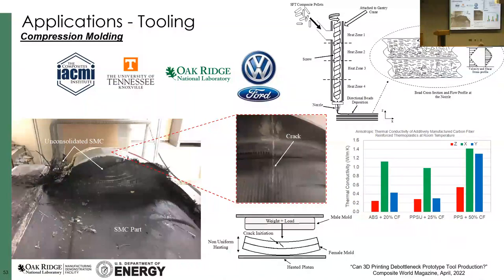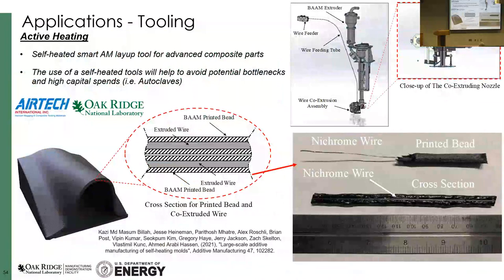Because the thermal conductivity, fundamentally, even in Z, and you see, first of all, it is anisotropic, right? But even the best among them on the ABS is about 1.1, and the one with 50% carbon, for God's sake, right? It's about 1.4. It's nothing. Like, good luck to heat up this tool. So how can we scale it up? There are two approaches. Either I move the heating source near to the molding surface, right? Or enhance the thermal conductivity of the material.